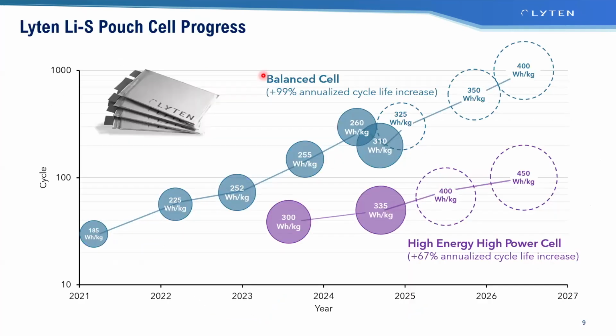So, what our roadmap looks like, these are normalized watt hours per kilo to our pilot line cell. It's been a slow, steady walk up the cycle life curve and up the energy density curve. One thing about lithium sulfur is the cycle life is always the most challenging part. These are full depth of discharge, practical cells, 25C, we're getting 200, 300 cycles. Most people in the battery world are like, really? You're doing that well? In a practical cell? I'm like, yeah. Most other people find that underwhelming.